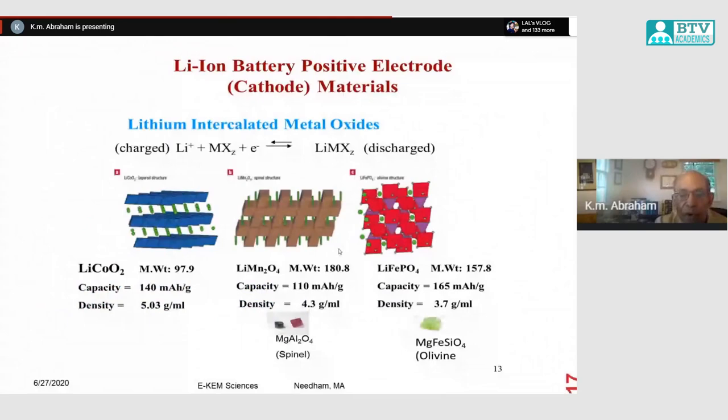So that is the chemistry of the graphite anode. Now, the intercalation electrode: as I said, the first intercalation electrode was cobalt oxide. Subsequently, people came out with other materials. Lithium manganese oxide is a three-dimensional material. You can see the lattices. These are open holes in the three-dimensional lattice, so the lithium can go in and out of that when you discharge and charge your battery.